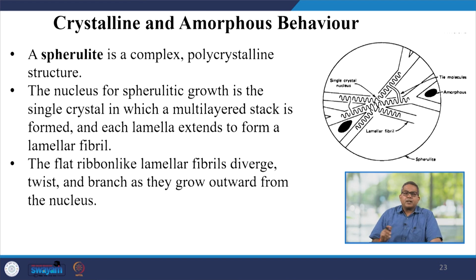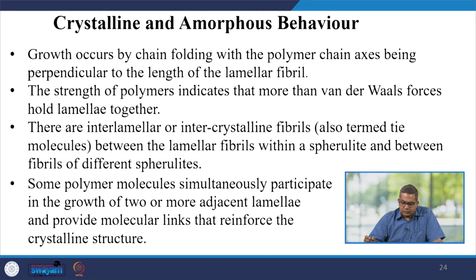Spherulite is a complex polycrystalline structure. The nucleus of spherulitic growth is a single crystal, from which a multi-layered stack is formed, and each lamella extends to form a lamellar fibril. The flat ribbon-like lamellae, like here you see, diverge, twist and branch as they grow outward from the nucleus. Now, the growth usually occurs by chain folding with the polymer chain axis being perpendicular to the length of the lamella.